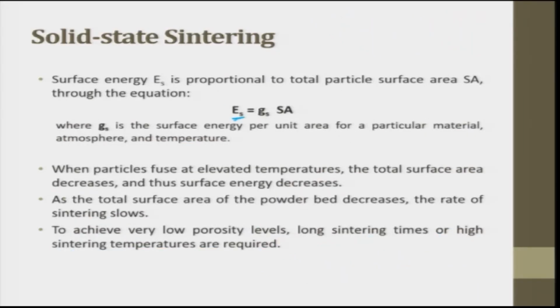The surface energy, so you can see here free energy ES. The surface energy ES is proportional to the total particle surface area SA through the equation. So, ES is equal to GS into SA, where GS is the surface energy per unit area for a particular material, atmosphere and temperature. So, this is a star. When particles fuse at elevated temperature, the total surface area decreases and thus surface energy decreases.